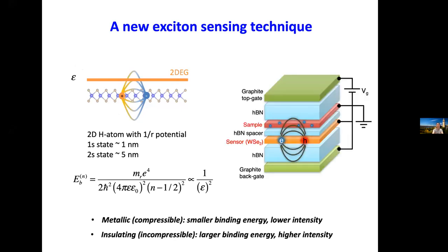So this is a realization of this idea. We have our sample, which is the Moire superlattice, and we place the sensor layer close to it, but not too close. We put an HBN spacer in between. The spacer is on the order of a nanometer, smaller than the 2s exciton Bohr radius, but thick enough to kill the electronic coupling between sensor and sample.